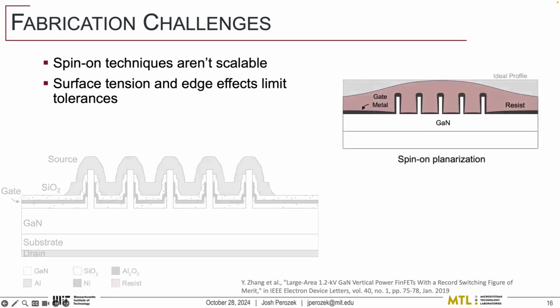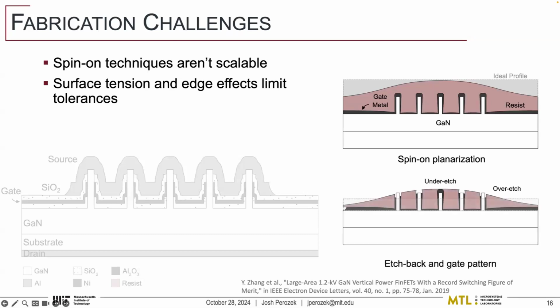But the problem is what actually happens when you spin on photoresist is it's never actually flat. You'll have surface tension and curing shrinkage and edge effects that all lead to a domed shape over your fin array. And when you etch that back, the profile stays there. So you're never going to have a very precise way of etching back this photoresist layer. And your device is going to have some potentially fatal defects within it.